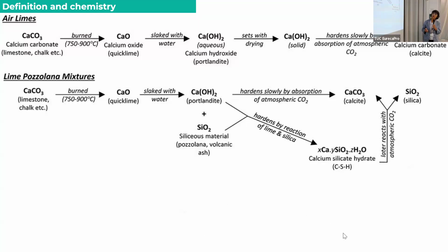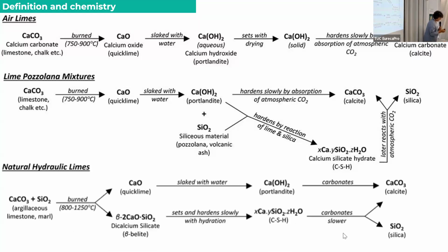If we proceed with the burning of limestone, but in those materials we also add some siliceous material, then another very important hydraulic component, the calcium silicate hydrate, is yielded, and this material can also produce, at the end, calcite and silica after the deterioration process.